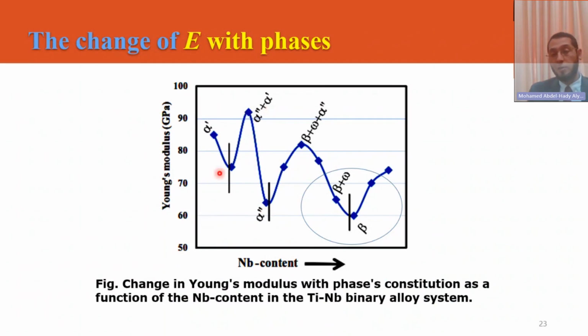But most of the elements follow the same geometry of how the phase changes are related to the Young's modulus. Among all these, we can see that the lowest Young's modulus, which is one of the targets, is around the single beta phase zone, with beta plus omega and other phases around it. So if we catch this point from the composition point of view, we will achieve the lowest Young's modulus, so the highest elasticity, which means the lowest stress shielding probability, and so on.